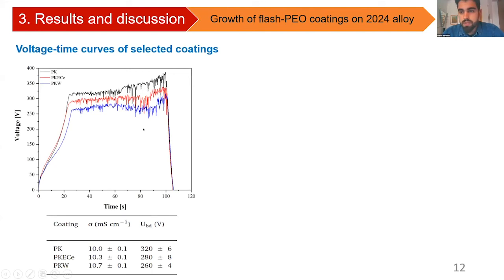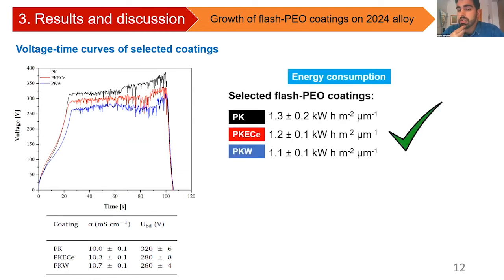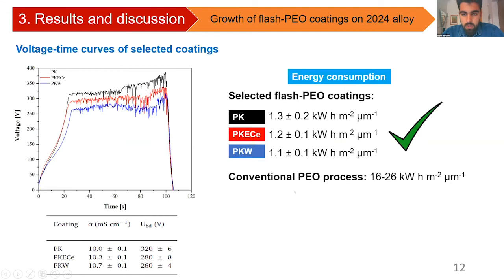Well, the voltage-time curves of these coatings reveal similar trends in all cases. For the inhibitor-free PEO coating, the black one, and the red and blue ones for inhibitor-containing coatings, cerium and tungstate, which reveal lower voltage values and lower breakdown voltage values also. The energy consumption of these coatings was significantly lower in comparison to the conventional PEO process.